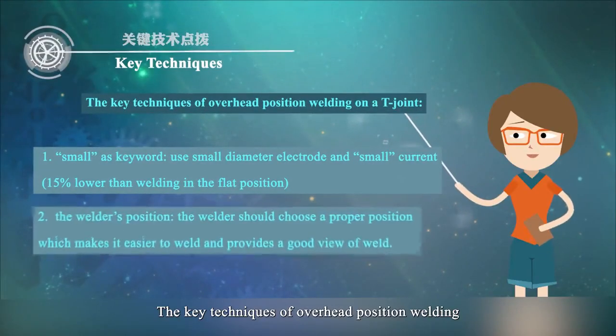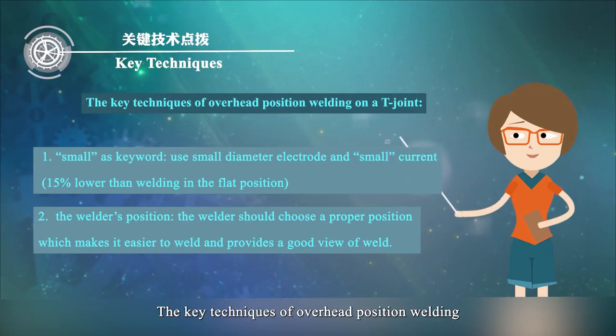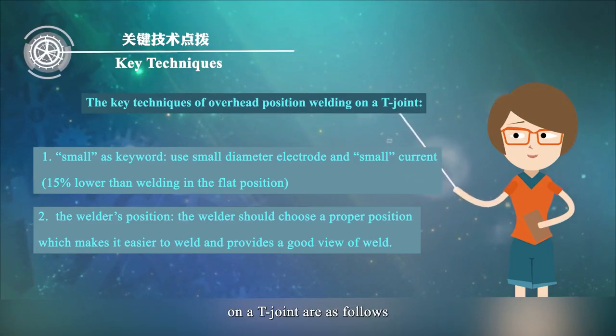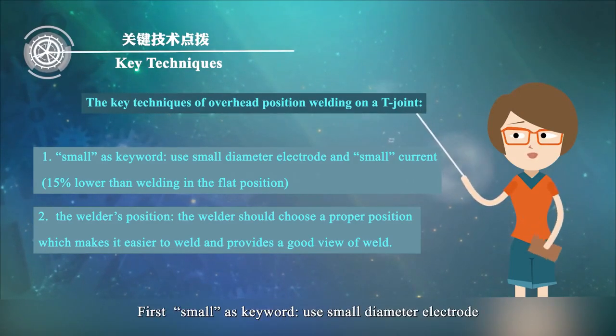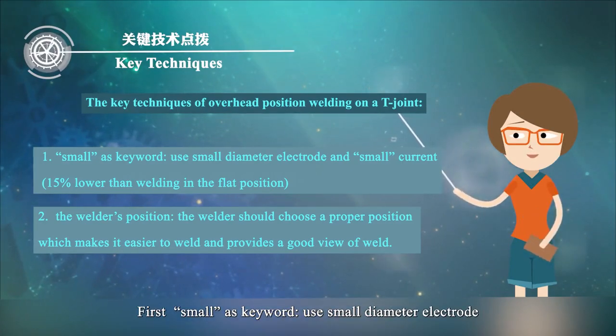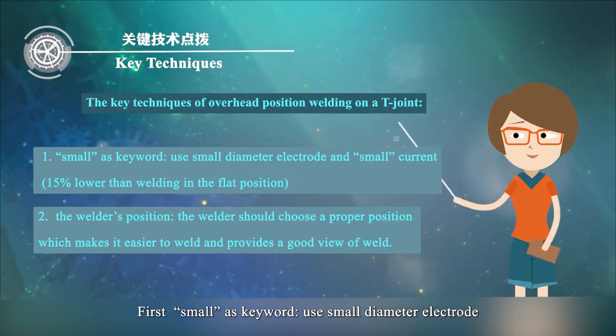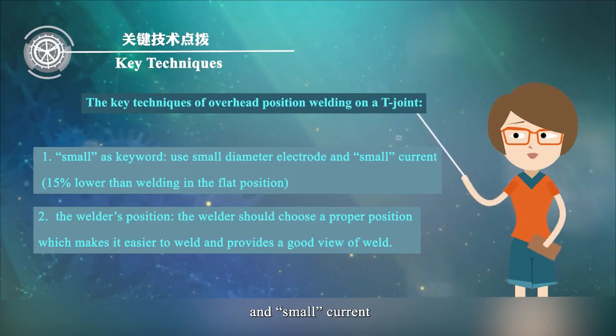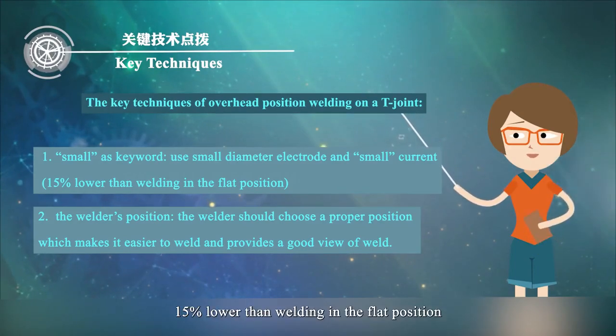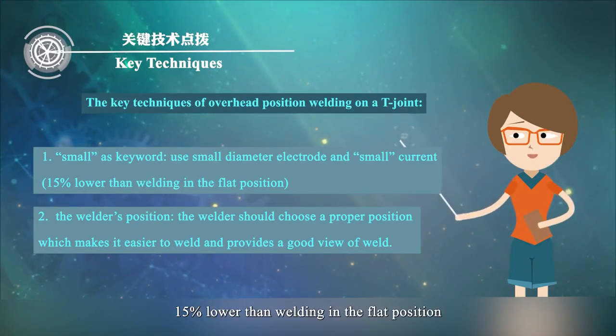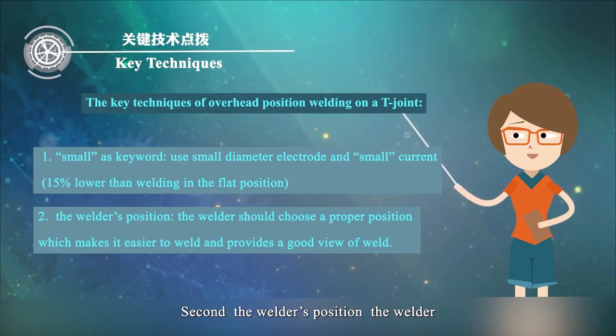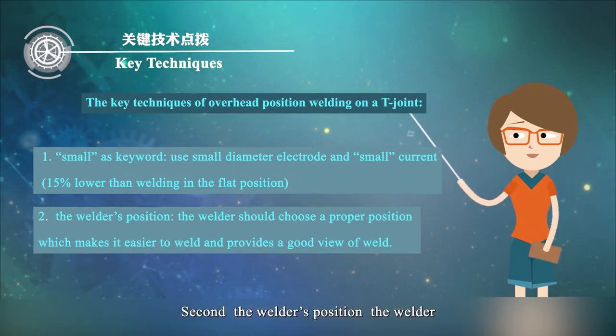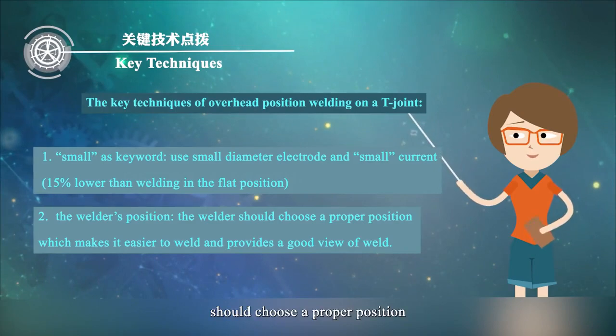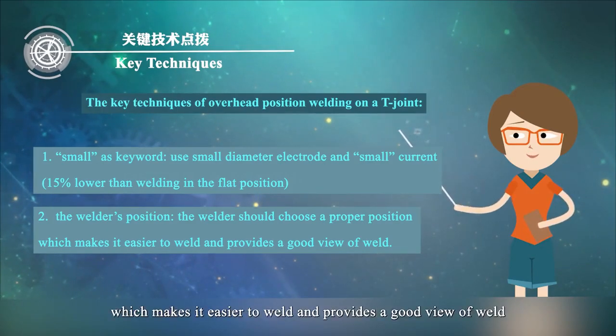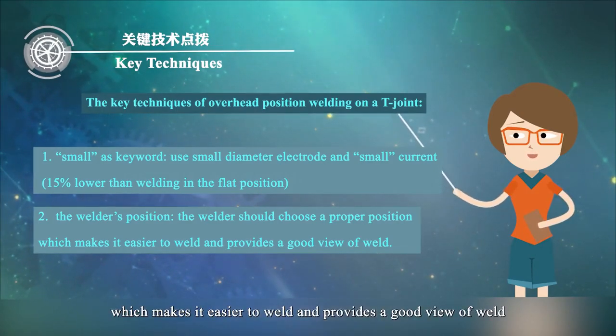The key techniques of overhead position welding on T-joint are as follows. First, small as keyword: use small diameter electrode and a small current, 15% lower than welding in the flat position. Second, the welder's position. The welder should choose a proper position which makes it easier to weld and provides a good view of weld.